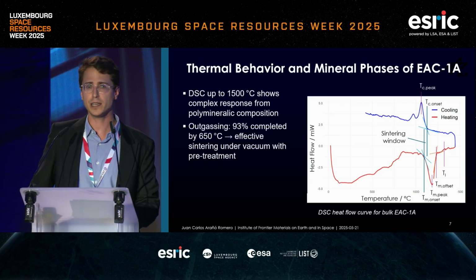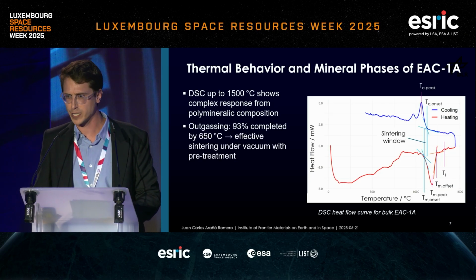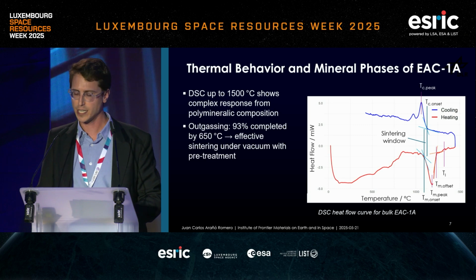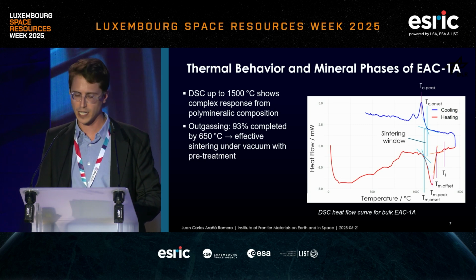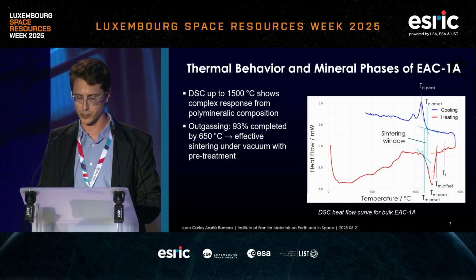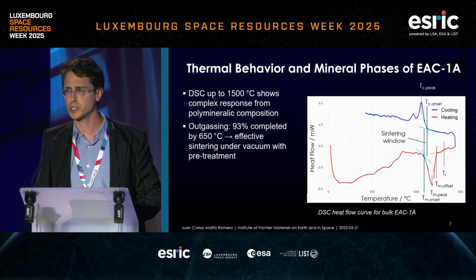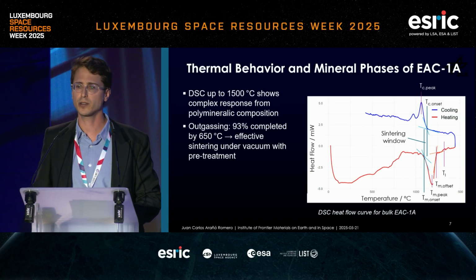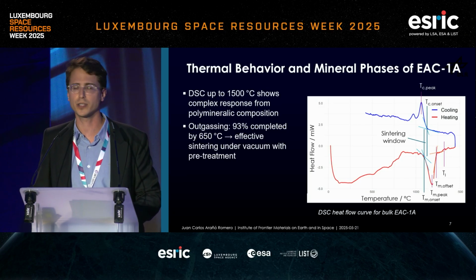And through TGA, through thermogravimetric analysis, we also saw that most of the outgassing happened up to 650 degrees Celsius. So this is good, especially under vacuum, because then the material could be pre-treated in order to help on a better densification when sintering under vacuum.